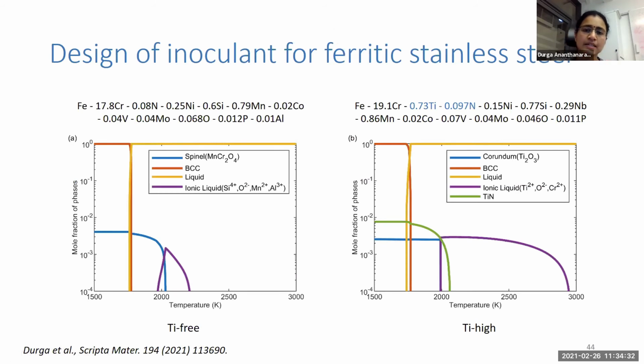So taking as a base the 441 grade of ferritic stainless steel, we tried to design two different compositions, one which does not have any titanium, and another which had the maximum amount of titanium nitride that could form. So we adjusted the amount of titanium and nitrogen in such a way that we can have the maximum amount of titanium nitride forming through the gas atomization process. We were restricted about the amount of nitrogen that we could add through that. So these two compositions were designed, atomized, and printed.